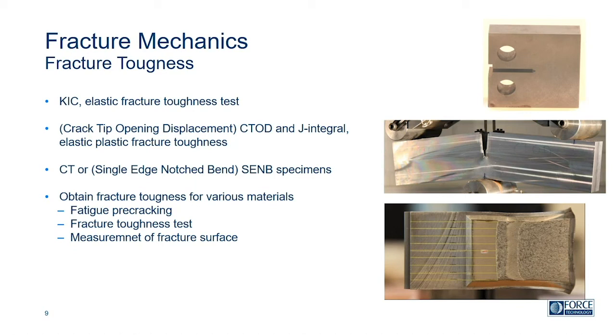What we have seen is that for cast materials, it has been quite interesting for some of our customers to actually get the actual fracture toughness and fatigue crack growth curves to be able to keep more material, or say another way, not discard the materials due to small defects, or to allow for larger defects in the castings. So that is one of the practical ways we have used this, or we know that it has been used.